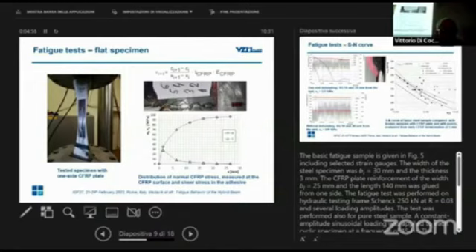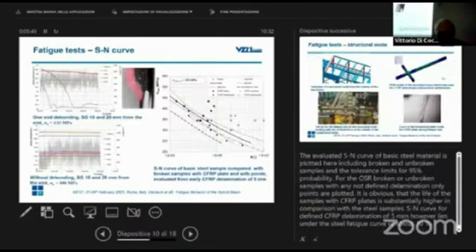Here is example of fatigue test of flat specimens. We have this CFRP plate 140 millimeter length, and we also measure the distribution of strains from the end of the CFRP, and according to this, we can make calculation. We can calculate this distribution of shear stress in the adhesive, and also the distribution of the stress of the CFRP plate. So you can see that after about 35 millimeters, the stress is stabilized.